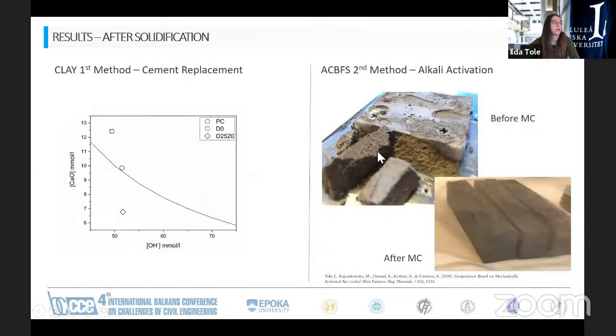So, and here you can see actually from the picture how these alkali activated materials look. This is the alkali activated material with a not treated air-cooled blast furnace slag. So it was not even possible to remove this material from the molds, while after mechanical activation, we had some samples that were comparable with ground granulated blast furnace slag.